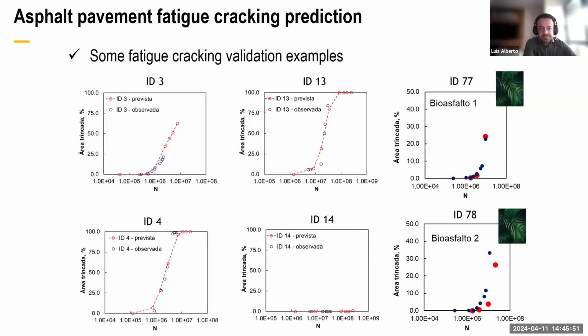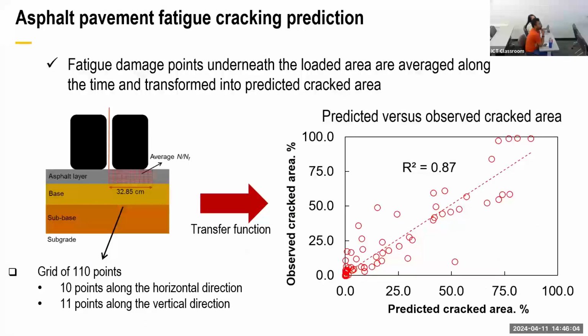Do you need to follow up? I have a follow-up. Okay, so also you mentioned that you predicted IRI and compared IRI. So how did you measure IRI in the field? The cracked area? The IRI, how was IRI measured? IRI was measured by using the laser profiler. It's a very common way to measure. We have some lasers, so you can measure the pavement longitudinal profile, and then this profile we put in the Golden Car algorithm, and so you have the IRI. So all this procedure is a very standardized procedure. We use the same ASTM standard as used in the US.